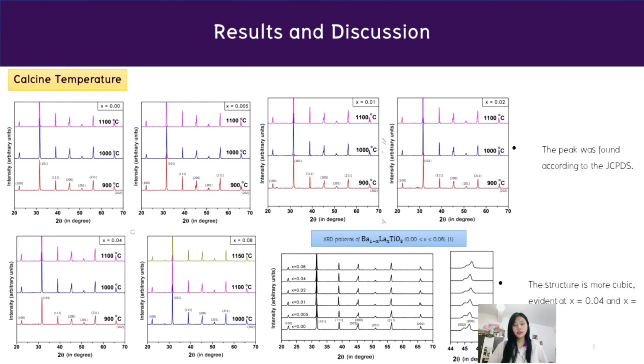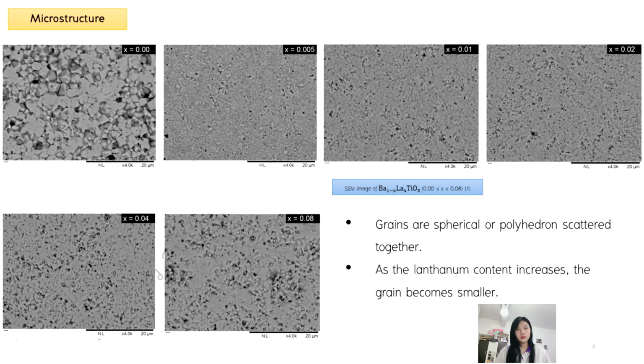You can see the XRD pattern of barium titanate doped with lanthanum. The peaks were found according to the JCPDS, and the structure is more cubic, evident at x equals 0.04 and x equals 0.08. This is the SEM image of barium titanate doped with lanthanum. Grains are spherical or polyhedral, scattered together, and the grain size decreases with increasing lanthanum concentration.